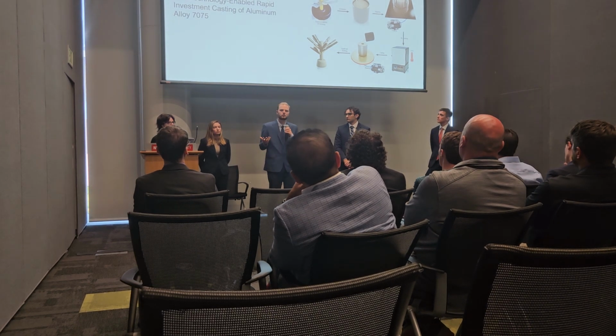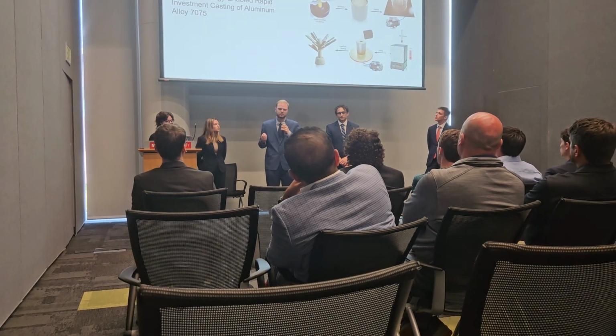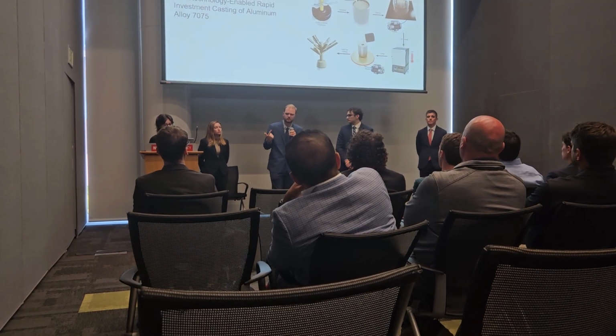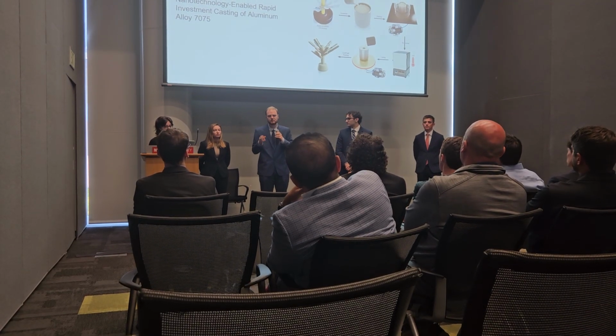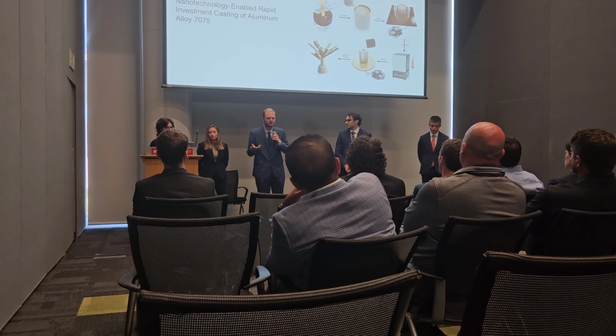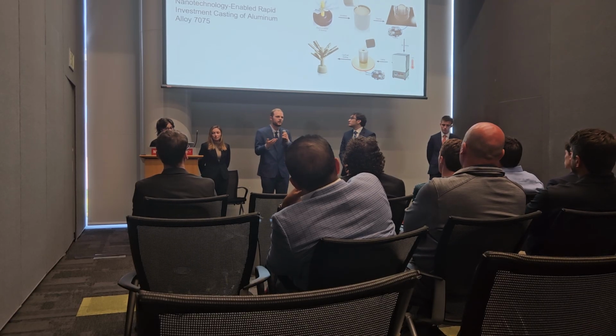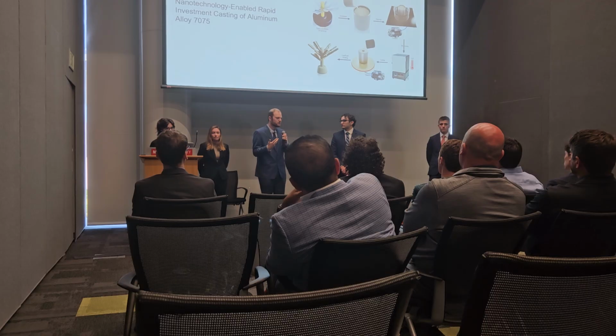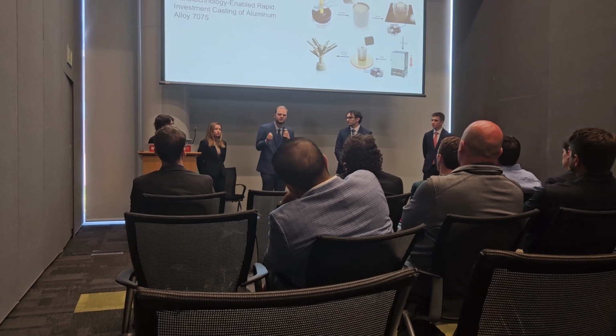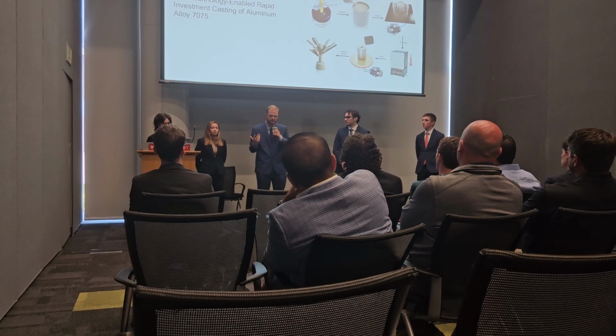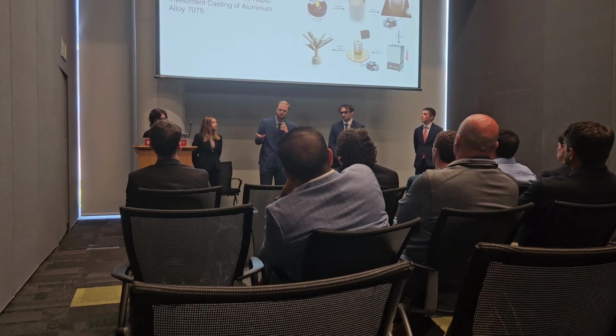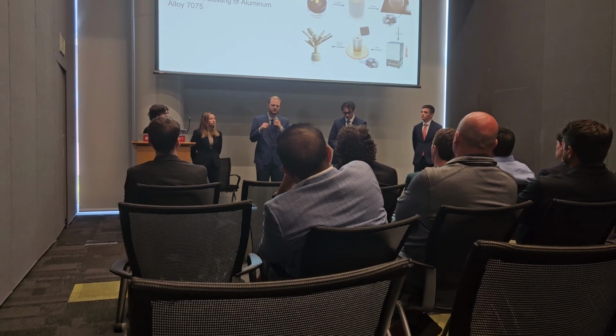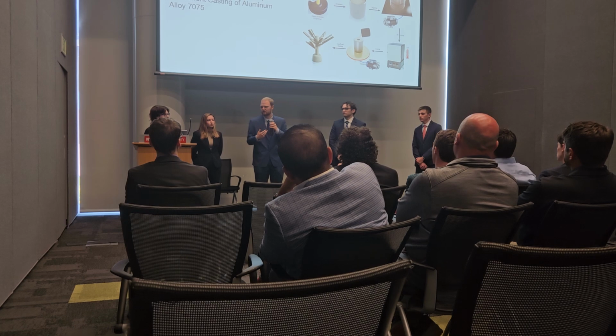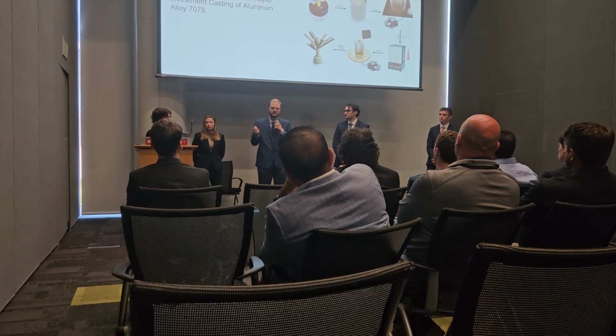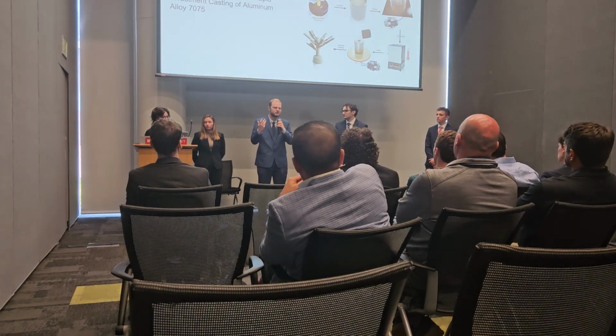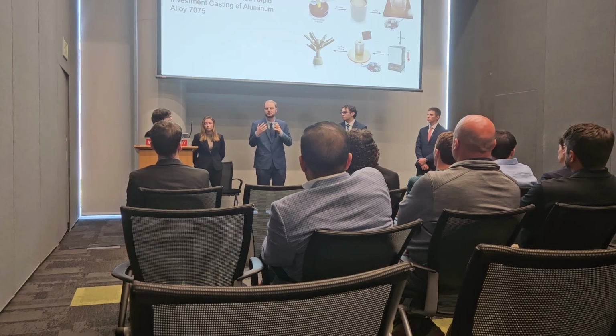Aluminum 7075 normally is a forged material, so to get the shape of the fins that we wanted, we would like to either cast or 3D print it. Due to its forged properties, when 7075 is cast or 3D printed, it leads to hot cracking and micro-fractures, which would give us lower stability when we are actually launching our projectile. One of the previous groups mentioned aluminum silicon 3D printing. We wanted to maximize our stability and minimize launch deformation, so that's why we decided to go with the aluminum 7075 body through the casting method.